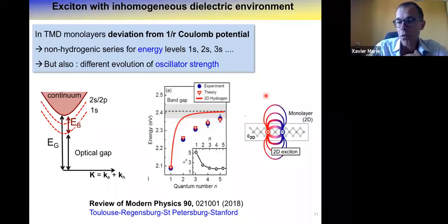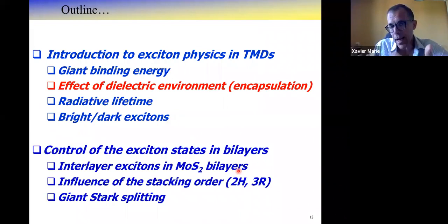So there are different approaches from calculation with different potentials. The one which is most used is Rytova-Keldysh, trying to describe in more detail and not only the very basic 1/r Coulomb potential we are used to. So from this, we can clearly see that the dielectric environment around your 2D layer will play a key role. This is not specific to 2D materials. Carbon nanotubes, for instance, excitons in semiconducting carbon nanotubes, you will face the same characteristic of the importance of the dielectric environment on the exciton.